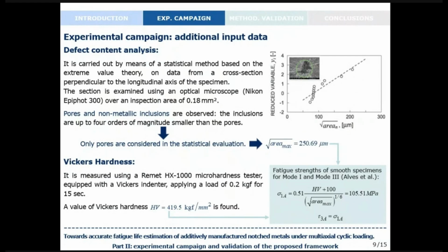And finally, the Vickers hardness is computed, obtaining the value reported here. And by employing these 2 values, so the Vickers hardness and the maximum defect size, we computed the fatigue strength of smooth specimens for mode 1 loading by employing the model I showed before, obtaining a value of about 105 megapascal. And then we conservatively assume the value for mode 3 equal to this one.